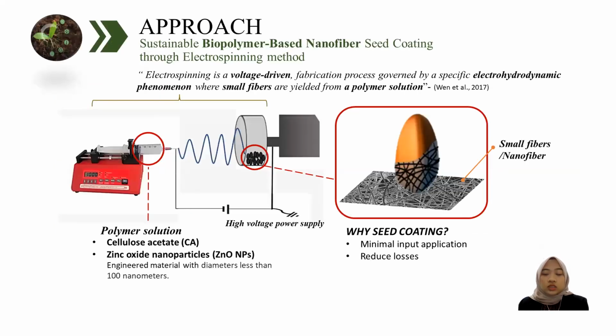The approach here is using the electrospinning process to produce the nanofiber. The polymer solution that we are focusing on here is cellulose acetate and also zinc oxide nanoparticles. The solution that we produce goes through the electrospinning process with a high voltage power supply that produces electrostatic force that can do the phase inversion from the solution to the solid nanofiber. And this nanofiber will be used to coat the seeds.